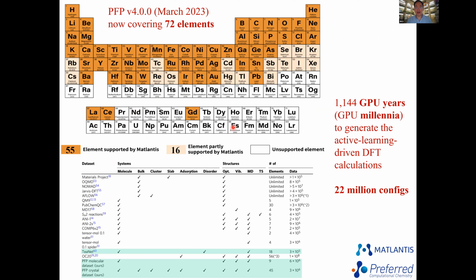And in developing this potential, they have used more than 1,000 GPU years of DFT calculations. So that's GPU millennia of DFTs. And also, we have used active learning, which is we always try to automatically find where the PFP is disagreeing with the DFT result. So it's sort of very self-critical. And it actively looks for regions in the chemical space where there is bigger error, and then tries to generate more configurations in those bigger error regions.